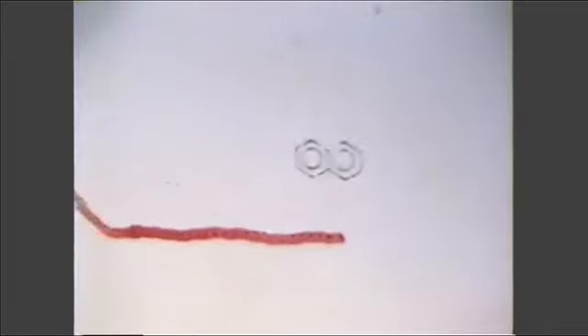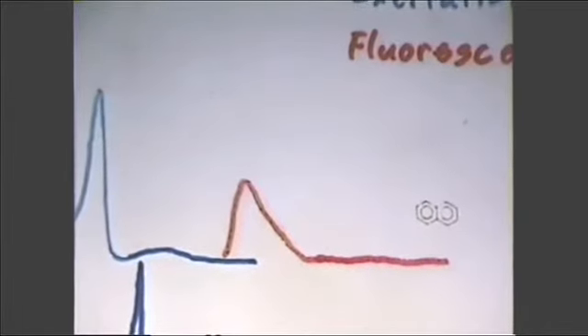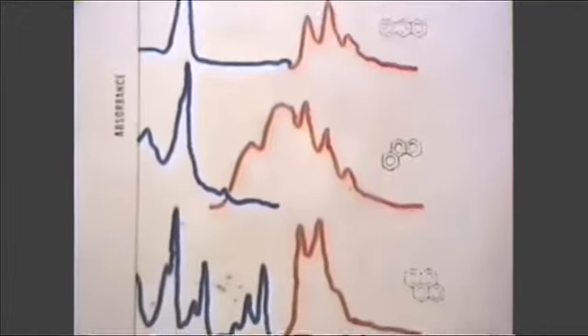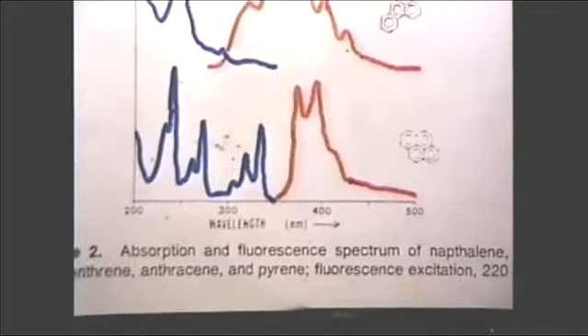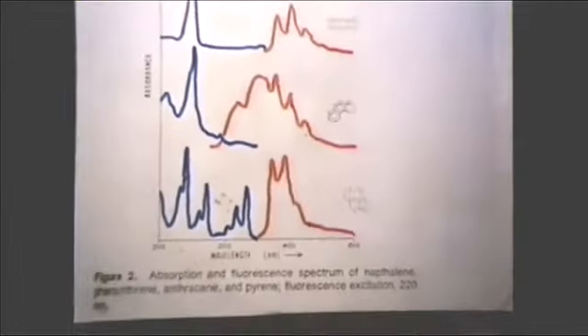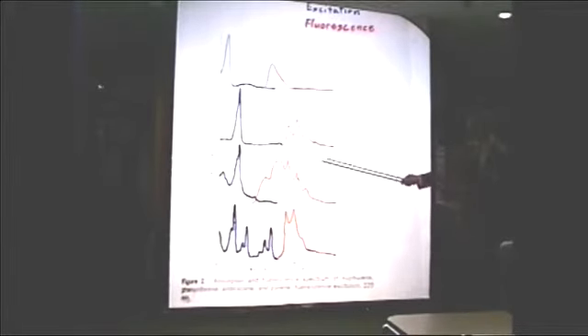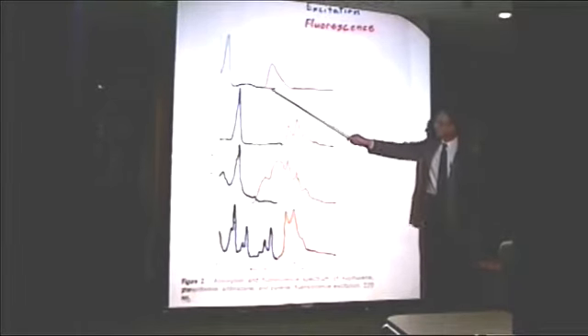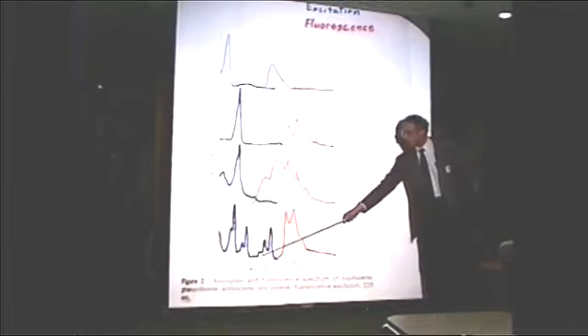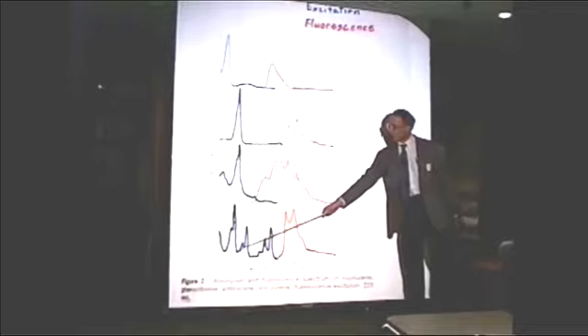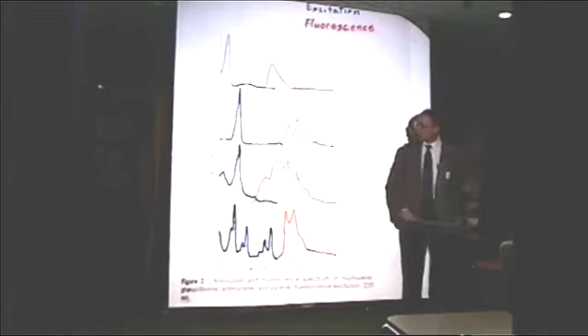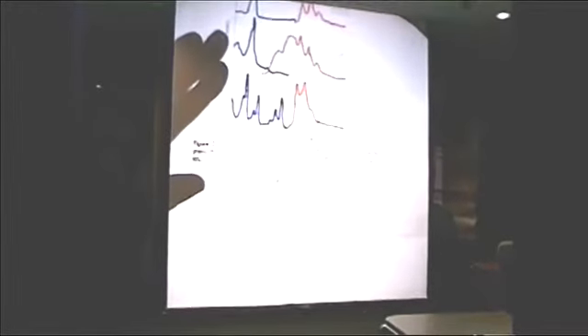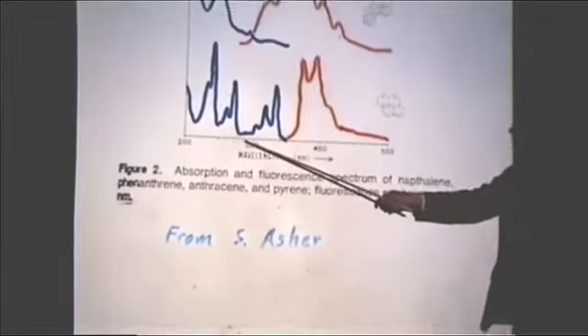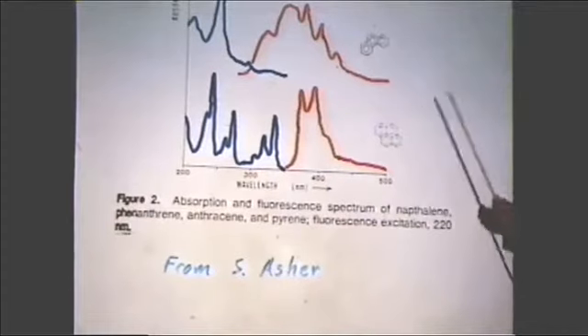Well, Asher looked at this, and what I have here is a transparency that shows the absorption or excitation spectrum as well as the fluorescence spectrum for a series of 4 molecules that are generic representations of what you might expect coke on a catalyst to look like. So here's naphthalene and anthracene and phenanthrene and something else that I don't know the name of, but anyway, it has 4 rings fused together. And what you can see here is that the low wavelength onset of fluorescence for all of these is about 300 nanometers. So if the excitation was done at about 250 nanometers, all of the Raman scattered light would appear in the region from about 250 to about 280 nanometers, and so we would avoid the fluorescence from any of these kinds of molecules.